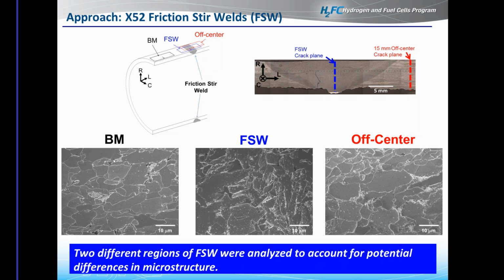So the base metal microstructure consisted of a ferrite pearlite microstructure. The friction stir weld didn't look all that different, although it did not have as much pearlite. It had more dispersed carbides throughout the microstructure. And then the off-center region looked fairly similar to the base metal. But we really wanted to get a good overall characterization of how the different microstructures are going to behave in this friction stir weld.